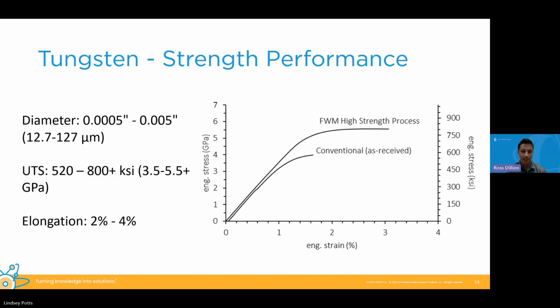So let's share the diameter ranges we can produce with the ultra strength, and that will run at, say, 5/1000ths of an inch down to 5/10,000ths of an inch, where tensile strengths come to about 520 to 800 plus KSI. And it's good to note with those strengths, we're still able to maintain pretty good ductility at 2 to 4%.